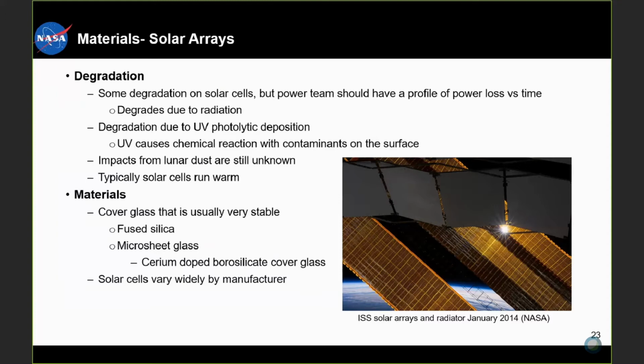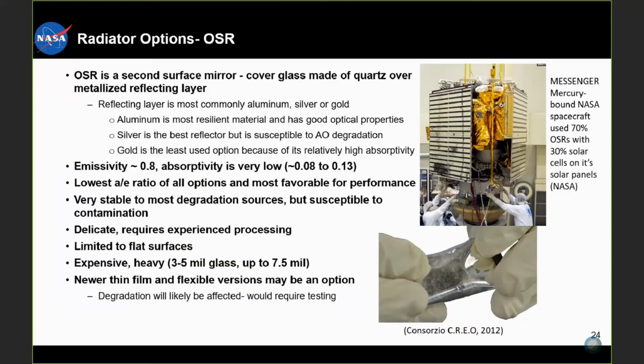So for the materials for solar arrays, a cover glass is used that is very stable. The first one is a fused silica, which actually has a greater resistance to darkening by UV and electron radiation. And the other is microsheet glass, which is a cerium doped borosilicate cover glass. This is used on thinner areas. It's not as fragile, but it is susceptible to UV radiation. But this is also directly related to its cerium doping. Ultimately, solar cells vary widely by the manufacturer, so there will be different thermal and optical properties chosen based on the environment or application. Next slide, please.